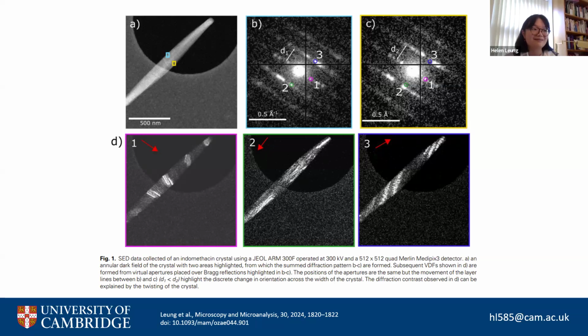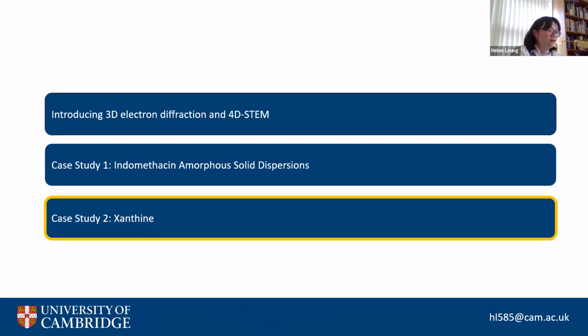But bearing in mind, we had to first successfully achieve structure solution through 3D ED before this was a meaningful experiment to do. And what the slide is showing here, and the contrast that you can see in the virtual dark field images, is potentially some twisting, but it's a really interesting example of the crystal microstructure and just being able to unlock that. But the key here is that's not really an insight that we can have without the 3D ED. Oh, and I should say that the indomethacin work is also published as well. So if you want to read up more about it, you can find that separately.